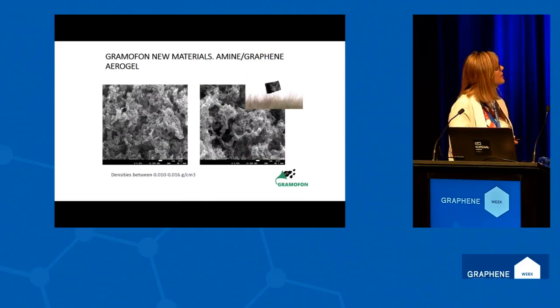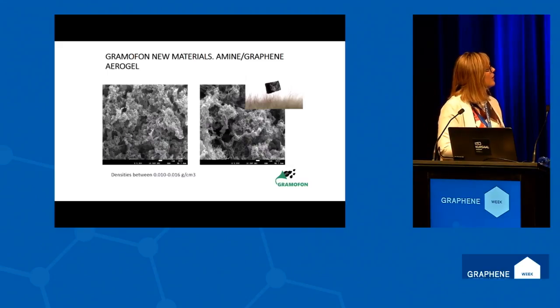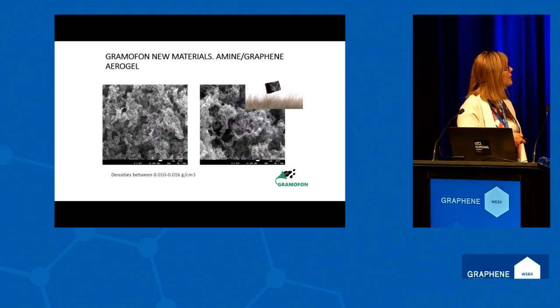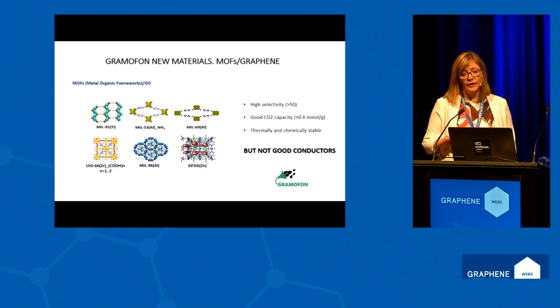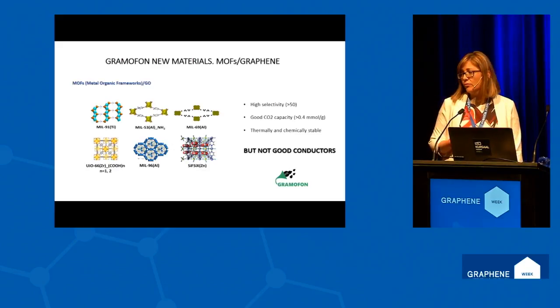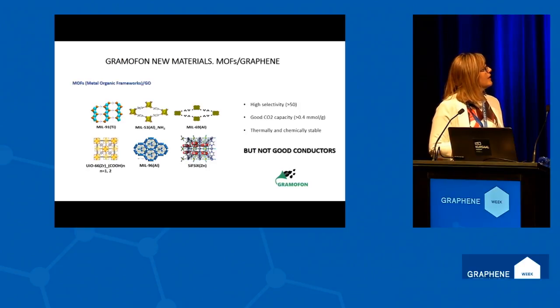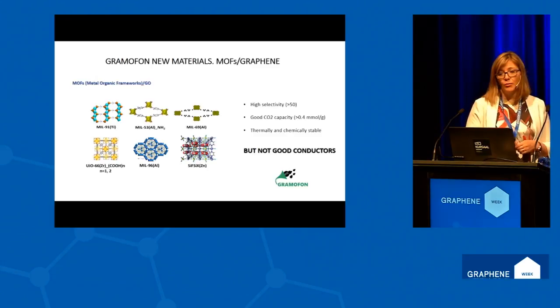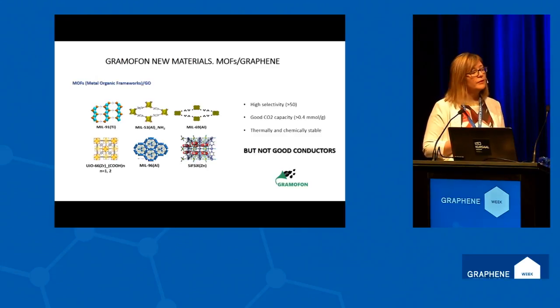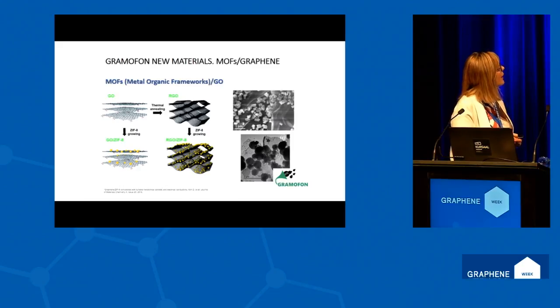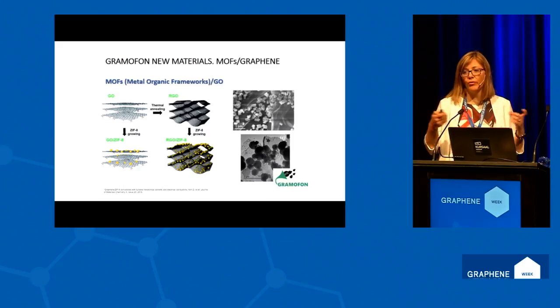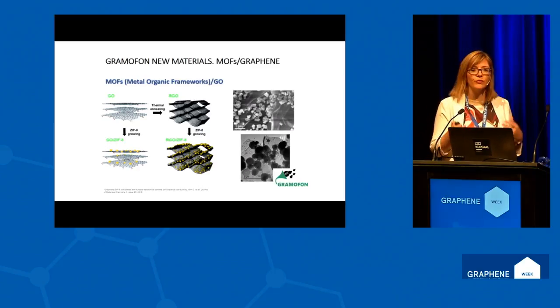Well, it's an image of different graphenes that we have obtained in the project, combined with amines. And we can also combine the metal organic framework with graphene. What is the advantage? The high selectivity, good CO2 capacity, and being thermally and chemically stable. But this type of MOF are not good conductors. So for that reason, we have to combine with graphene. So combining with graphene, we have all the advantages from each material.